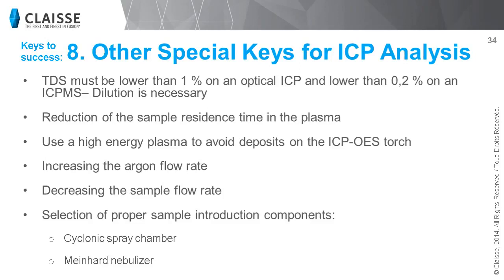When running a sample prepared by fusion on an ICP, a few tricks may help you ease your analytical process. On an ICP OES, it is best to keep the TDS under 1% and below 0.2% for ICP-MS, so appropriate dilution may be necessary. In order to avoid deposit on the ICP torch, reduce the sample residence time in the plasma and use high-energy plasma. Also, decreasing the sample flow rate will help to decrease the amount of salt in the ICP chamber.